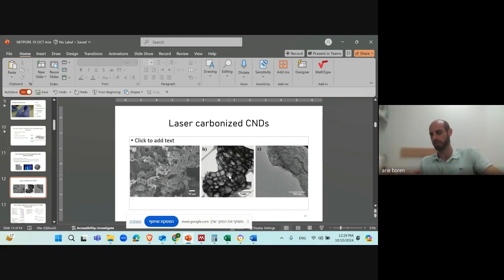So the graphitic cores of these nanodots, carbon nanodots, are integrated together to form larger graphene particles. Okay, so the holes here are caused by the pressure of the released gases, but the walls of these compartments of these bubbles are made up of graphene, and we could isolate a single graphene sheet. In TEM, it looks very similar to the graphene that I showed you before, made of the graphene oxide. It is much more crumbled, again, because it is made of the smallest building blocks.